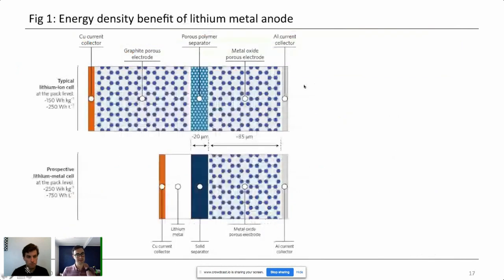Figure one, they show a schematic similar to what I've shown in terms of the size to scale of each of the layers in a battery. So here on the right, they have an aluminum current collector. Then you have the cathode active layer, the porous polymer separator, the graphite layer, and then on the left, the copper current collector. All of these layers are roughly to scale, more or less, for a lithium ion cell.